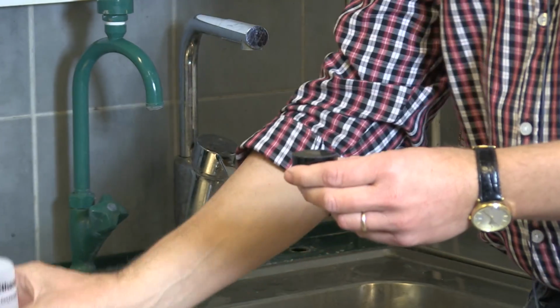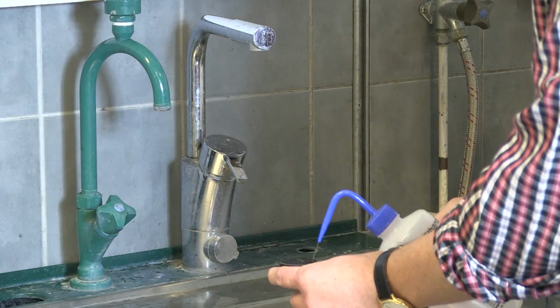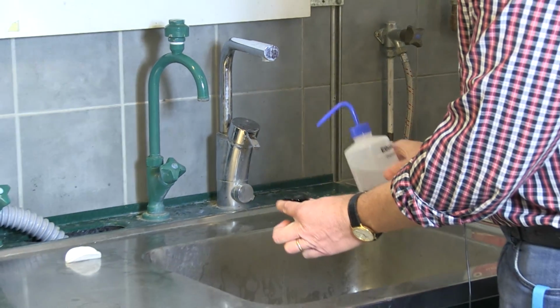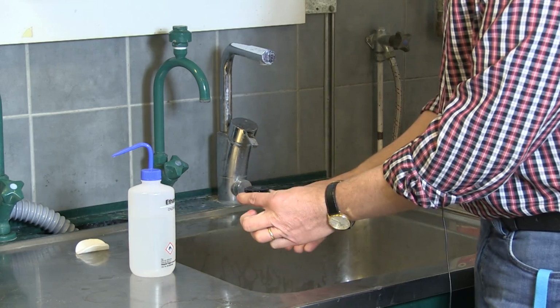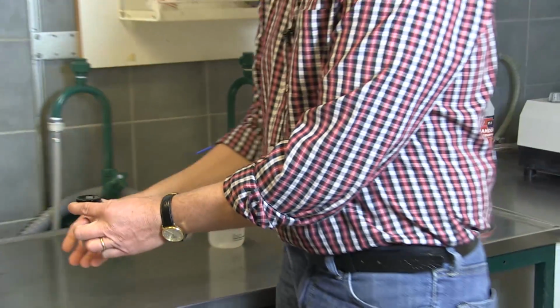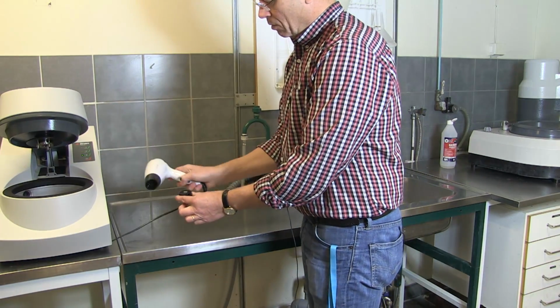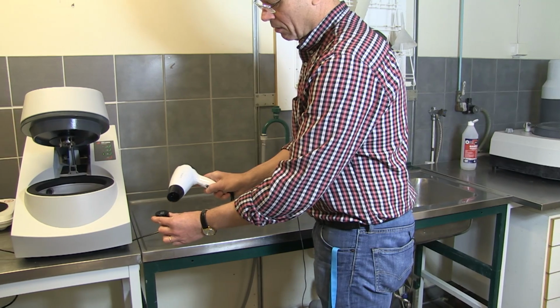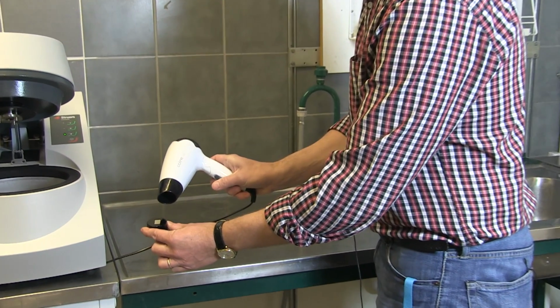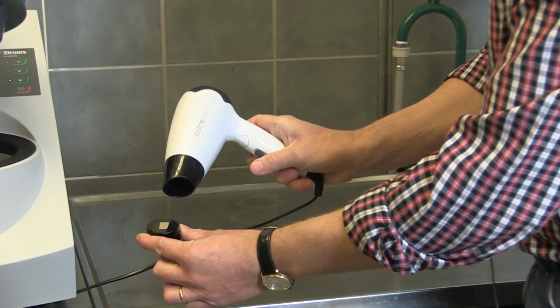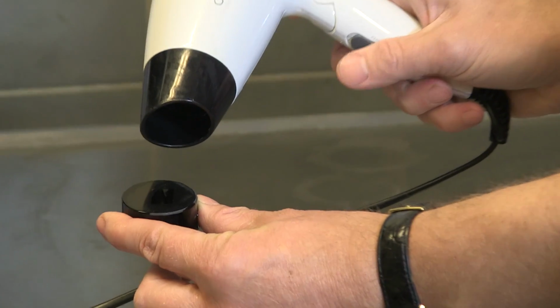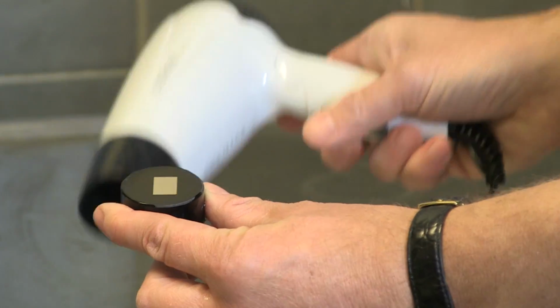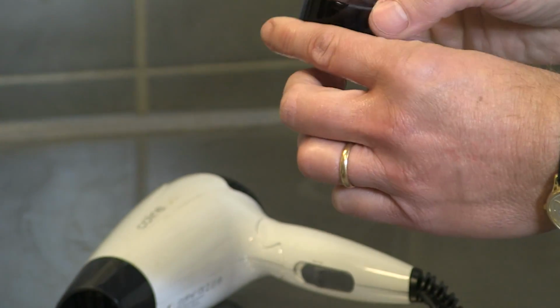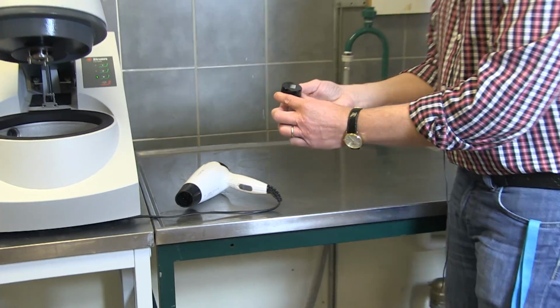If you just rinse away the water with ethanol, like this, and leave a layer on top, you can also use the fan to dry away the ethanol from the surface. It also works pretty well, but I prefer cotton, as I said before.